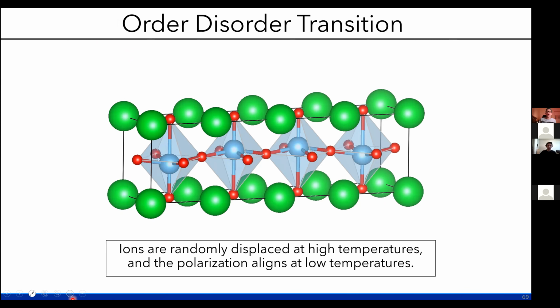So sometimes at high temperatures, we have the ions displaced, but some are down and some are up, and the average polarization is 0. But then as we lower the temperature, all of these ions align, and we again achieve our ferroelectric state. And the type of transition that's happening in the material affects the properties of the material and could give us information about the relationship between ferroelectricity and superconductivity.